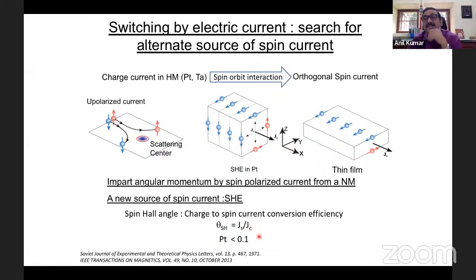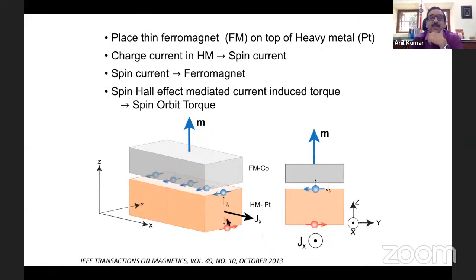Platinum has an efficiency of 0.1. So that means you have a ratio of spin current to charge current of 0.1 in platinum. You will see that in the remaining part of the talk, I will be discussing platinum. So now, you have a platinum layer. On top of the platinum layer, I deposit a cobalt layer, which is magnetized perpendicular to the plane of the system. If I pass electrical current, this current will accumulate spins on this surface, and these spins will exert a torque on this ferromagnetic material, and that torque will switch the magnetization.